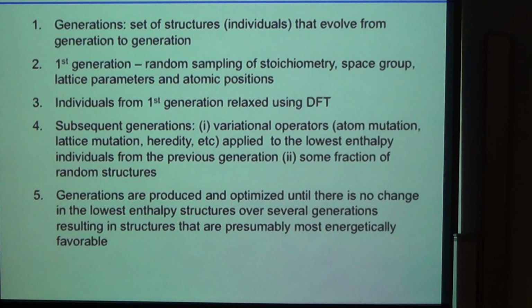So how does this evolutionary crystal structure search method work? You start with a random configuration of structures. Actually you create a generation. You have hundreds or several hundred of these random structures. This is your first generation, the population of your generation. Basically this is a random sampling of the stoichiometry, space group, lattice parameters, and atomic positions.